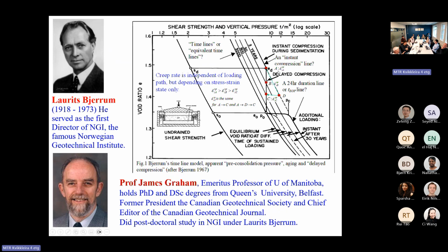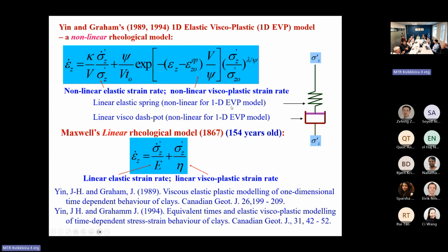And you can see here is a stress, here is a strain. This is a strain, stress point. But here, the same stress, but a strain which is different. So actually, the viscoplastic strain rate is dependent on the stress and strain point. So when stress is constant, saying the viscoplastic strain rate is constant is wrong. Actually, this rate decreases with time. So this term can describe this decrease gradually with time.